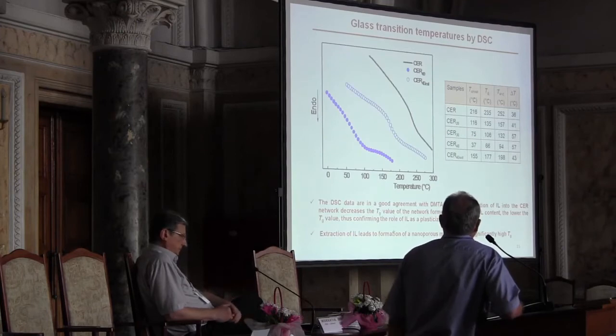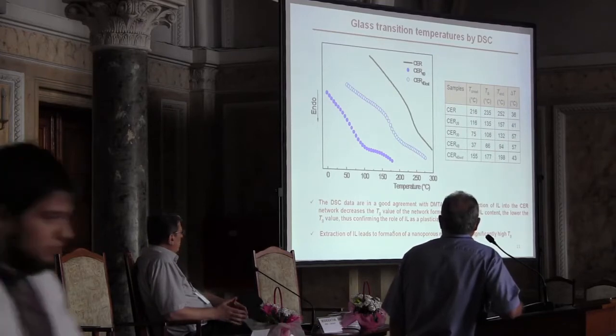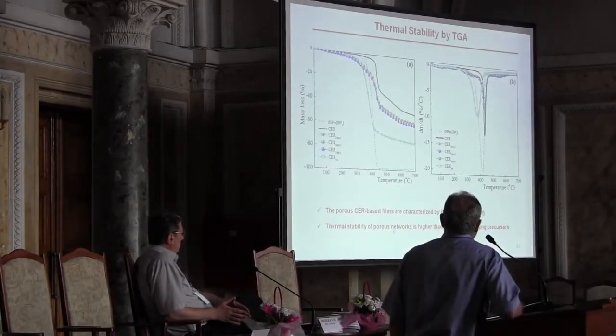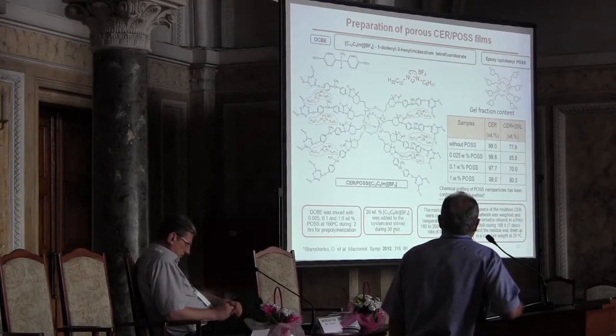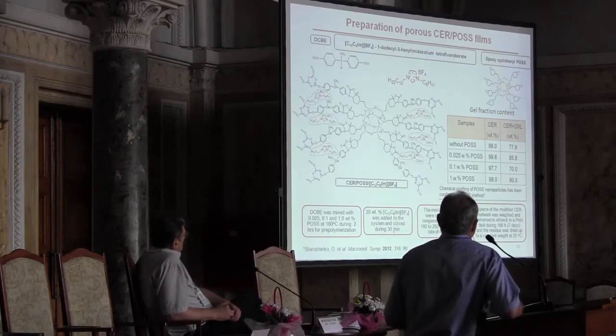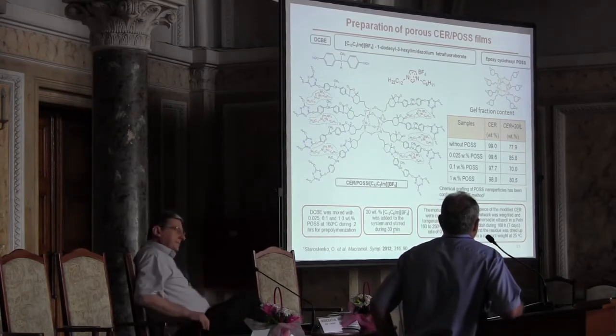Also, we can draw the same conclusions using the results of DSC investigations. Thermal stability for all the samples was around 400 degrees centigrade. And now some information about nanoporous nanocomposites of CER/POSS films, polyhedral oligomeric silsesquioxanes.